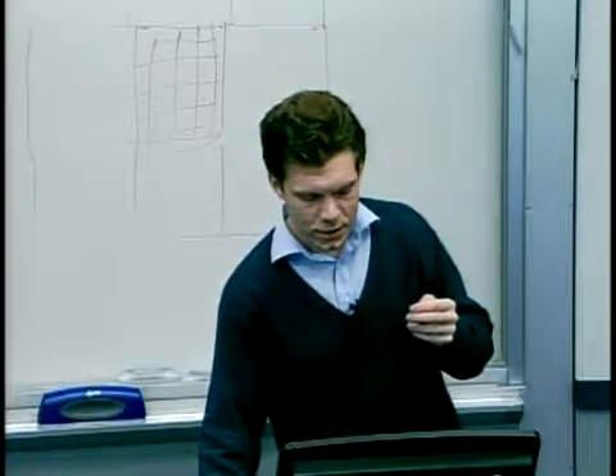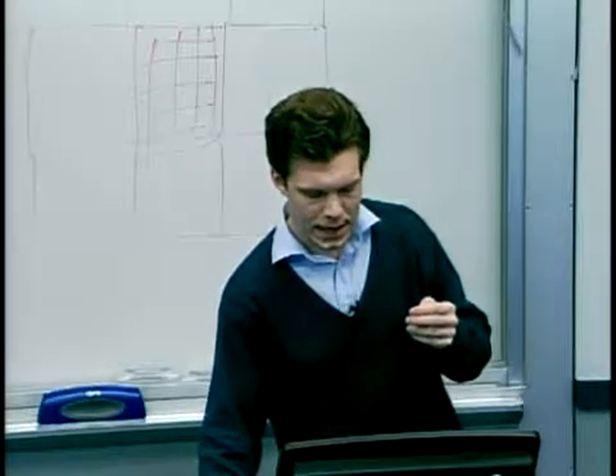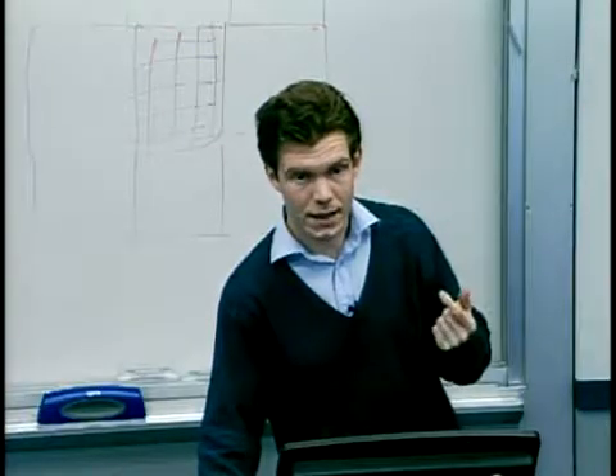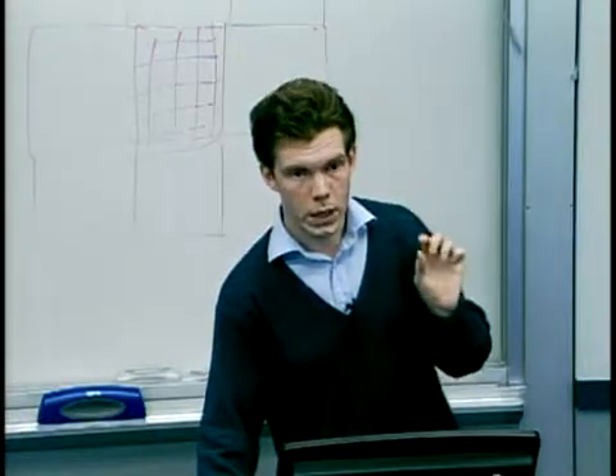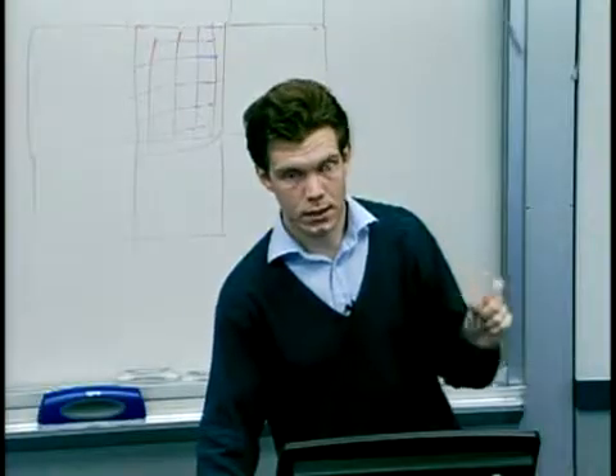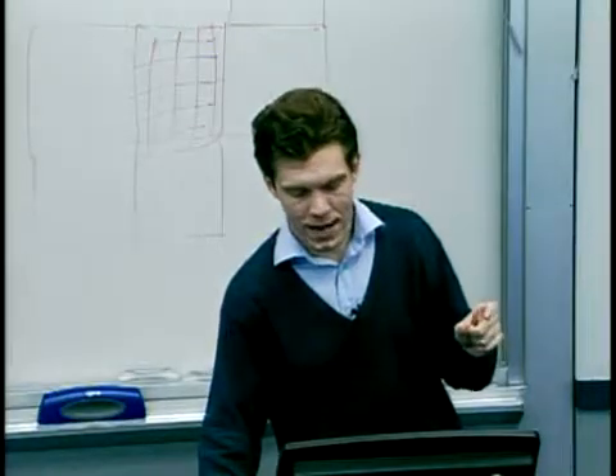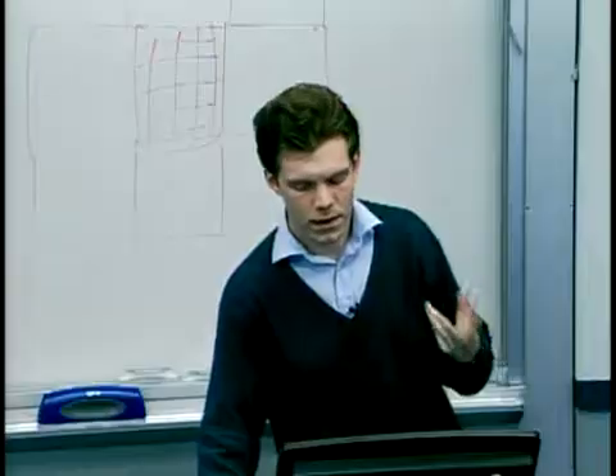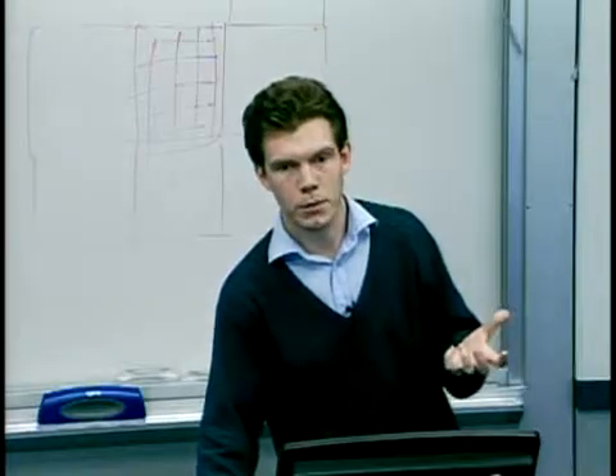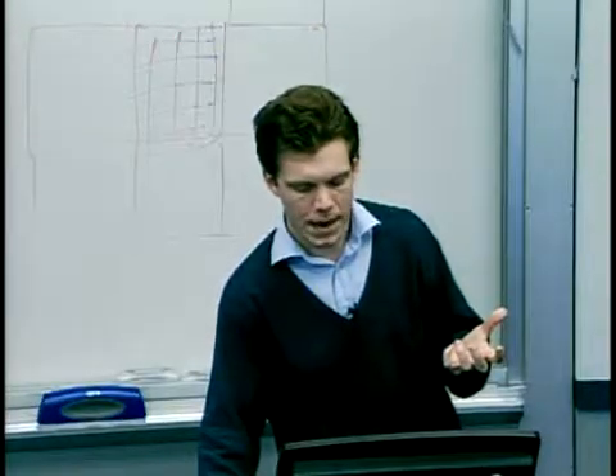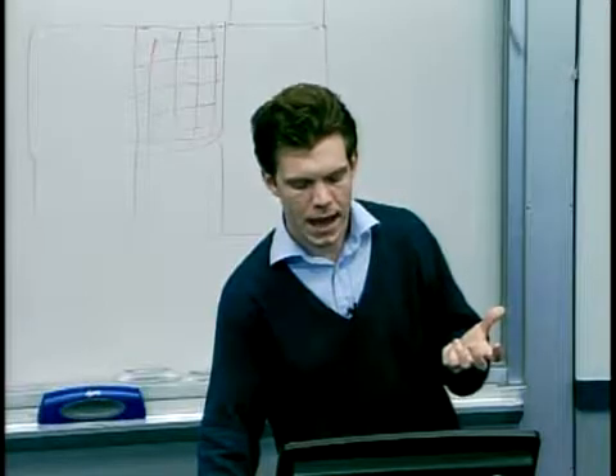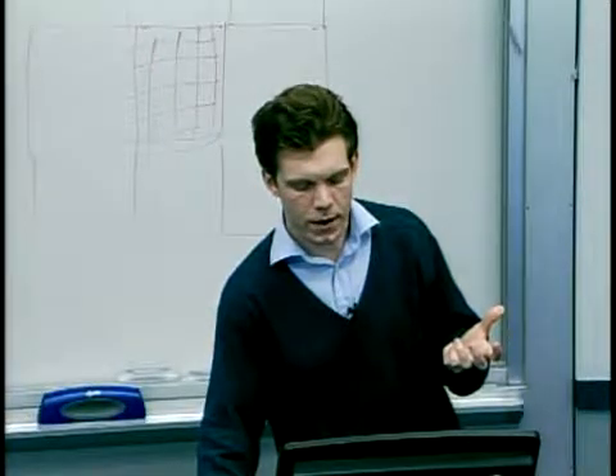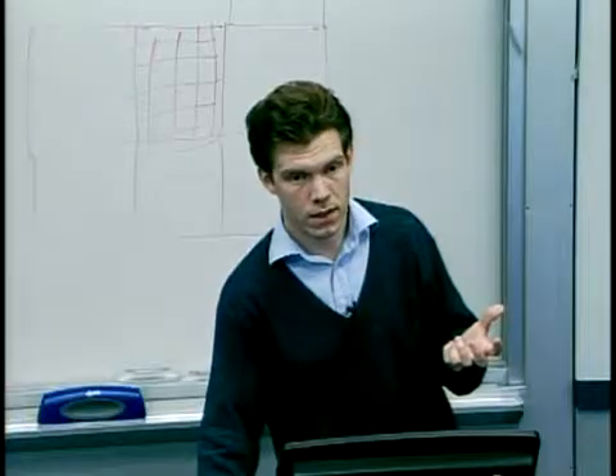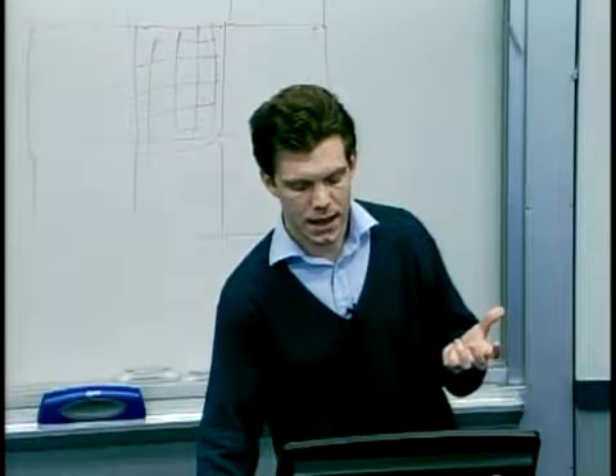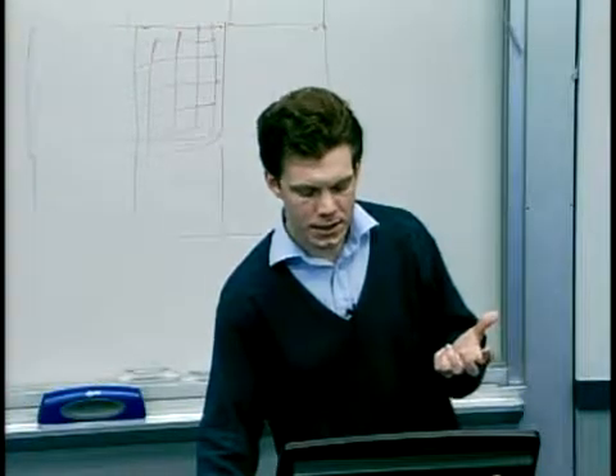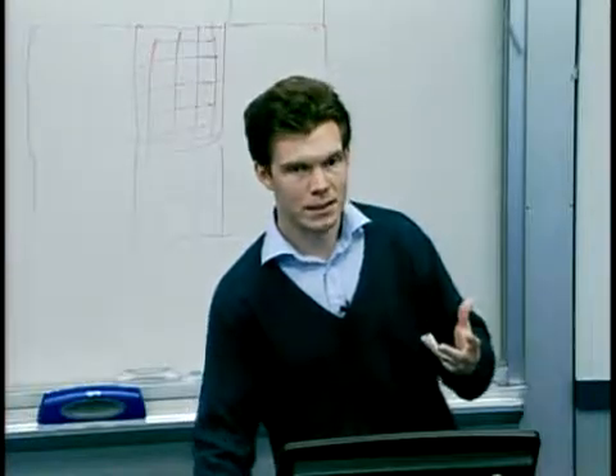The experimental data is shown in black underneath, and the prediction of the linear elastic model, with only one fitted parameter, the Young's modulus, is shown in red. And you can see that there's remarkable correspondence between the two. We get both a prediction of how far on average material penetrates cavities of a given diameter, and also we do capture these interactions of patterns of different densities.